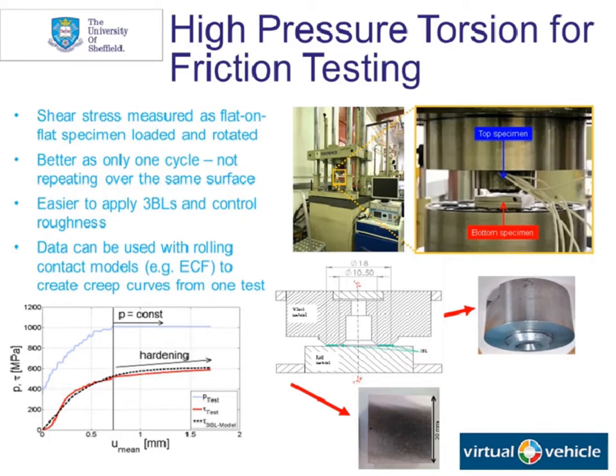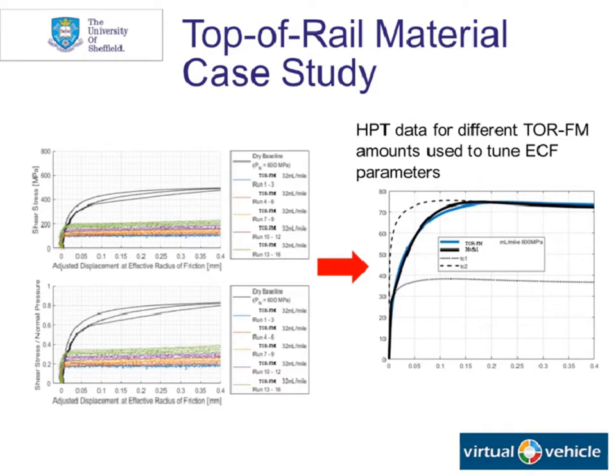Just wanted to show a little case study of how the HPT data can be used alongside something like the extended creep force model to enable us to do full-scale predictions. So on the left-hand side here, you can see some measurements we took with a top-of-rail product. So this would be applied from either an onboard system or a wayside system onto the top of rail to be picked up by the wheel if it's wayside and carried down the track. These are primarily applied to give you a kind of medium level of friction. Remember back to that earlier plot. That has benefits in terms of energy saving, but also in terms of wear and rolling contact fatigue reduction, noise reduction, and so on.